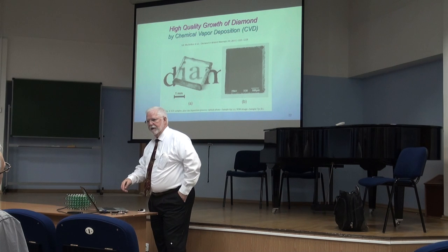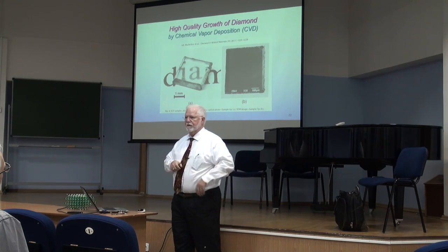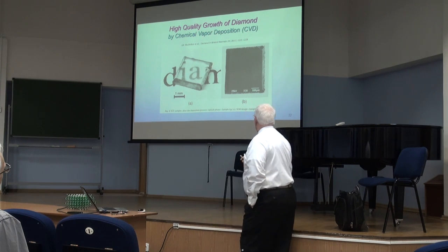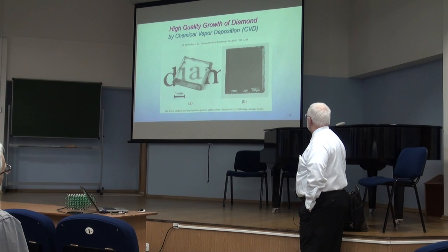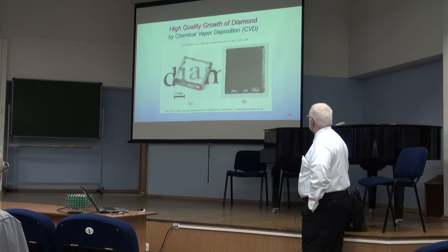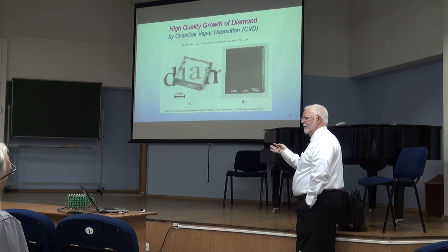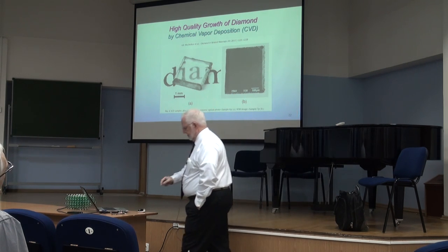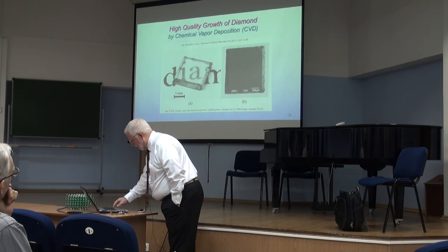The real point I want to make is that with CVD, we control the process and we can do it reproducibly. I also wanted to show an excellent example of a single crystal epitaxial layer that's been grown here at IAP, where you start, this was a 2 millimeter single crystal, and they grew, it looks like about 1/4 of a micron to 1/2 a micron of high quality epitaxial diamond on it. This actually forms the basis of what I'll talk about in our Mega Grant program.